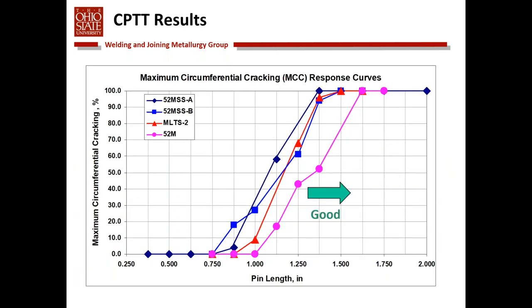Some other examples of some filler metals that we've evaluated for the nuclear power industry. 52M, we know, has pretty good weldability, resistance to cracking in actual practice. Some of these other materials that have higher niobium contents tend to be a bit more susceptible to solidification cracking. And again, the Cast pin tear test is able to differentiate that.